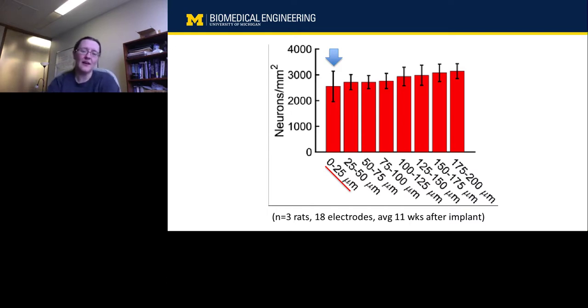And you can see here at 0 to 25 microns from the electrodes, we have a really nice density of cells. There might be some small decrease right near the electrode, but so far in 18 electrodes, it's not statistically significant compared to control brain, which you can see at 100 microns plus away from the electrode. And I think that, while we're really focused on neuroscience applications of this probe, this does strongly suggest that there's going to be safety implications if we can eventually use these electrodes for a variety of clinical applications. There's just many fewer missing neurons within 150 microns of the electrode.